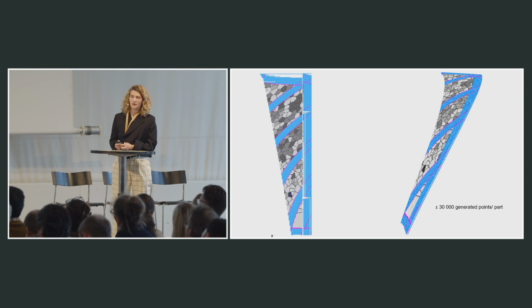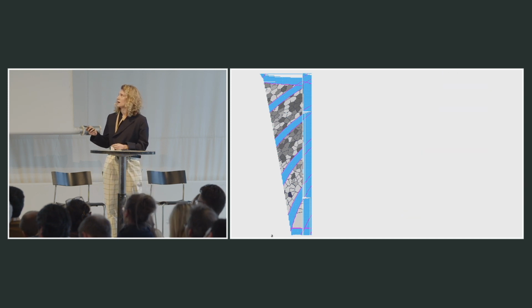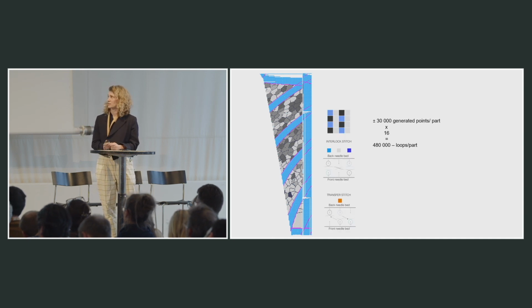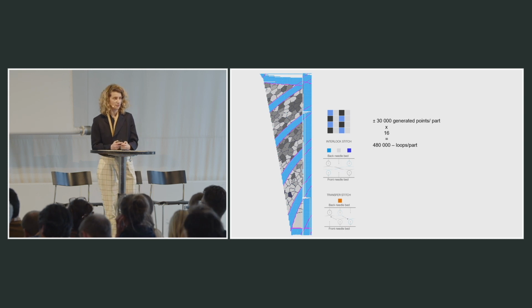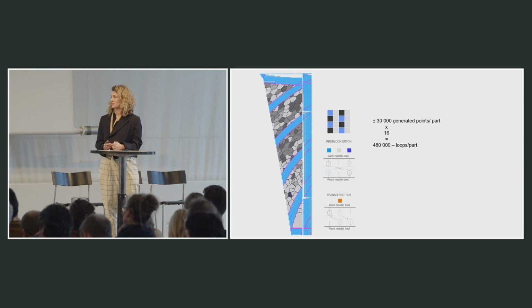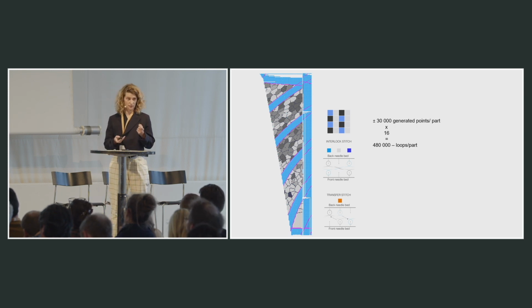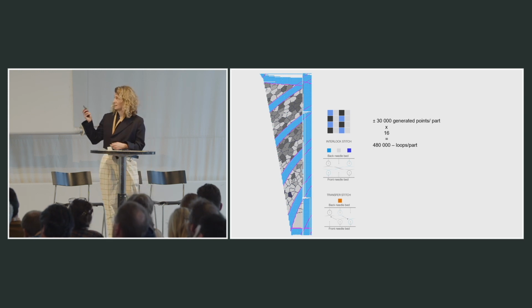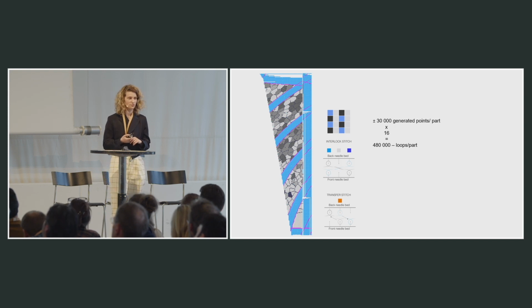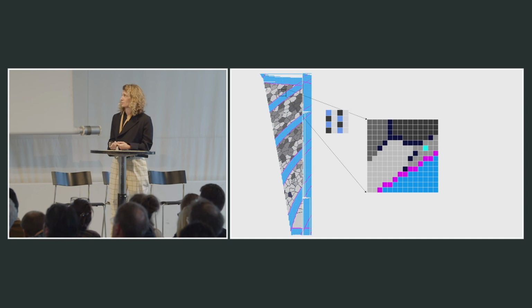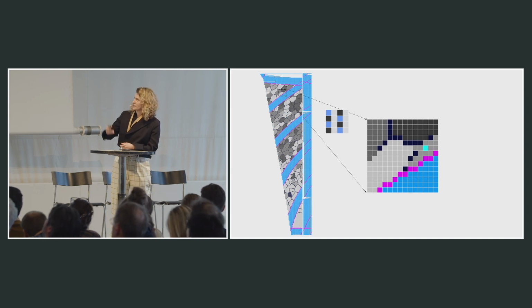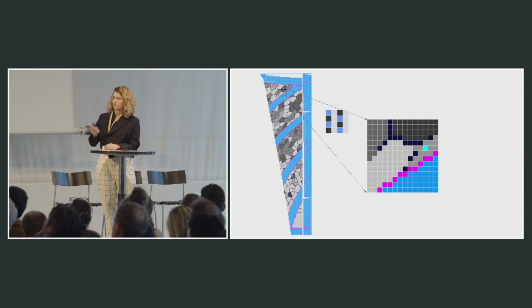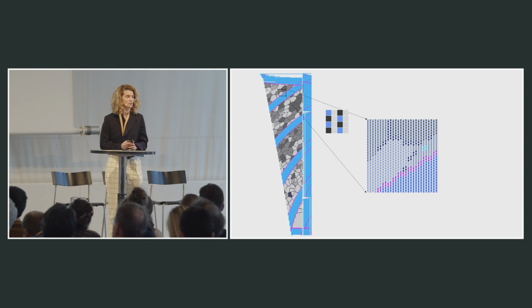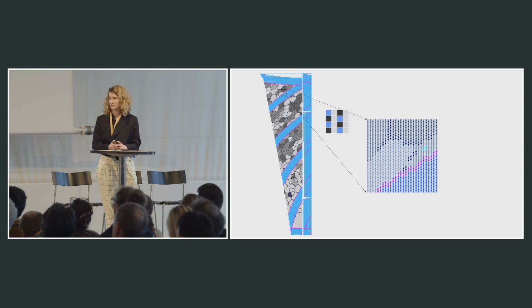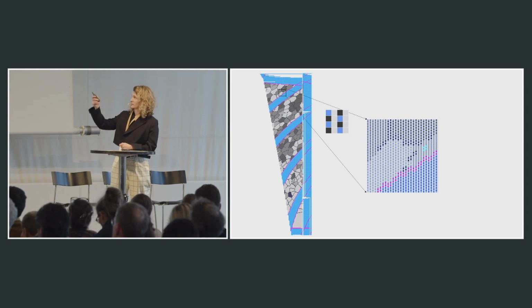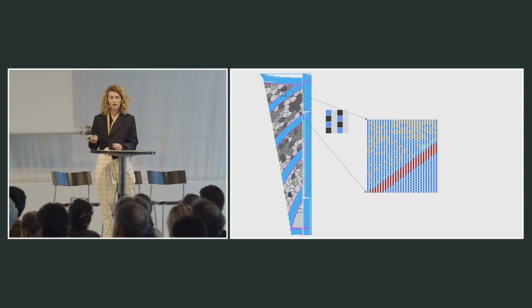Now, we take that type of generation, and actually each one of those points that you see in the 2D representation of the pattern represents a grid of 4x4, so it actually represents 16 units within the fabrication file, which has specific operations that allows us to introduce that porosity. That means that in the end, in terms of production, that's about 500,000 points that we needed to generate in this way, which means that we needed to have a post-processing step directly on a bitmap. So each one of those little pixels you see there that turns into those 16 comes from a piece like this that then gets processed into a bitmap that looks a little bit like that. And this is then further processed to add those densities based on our color gradient, so our darker or lighter shades of gray, to have those openings within it.